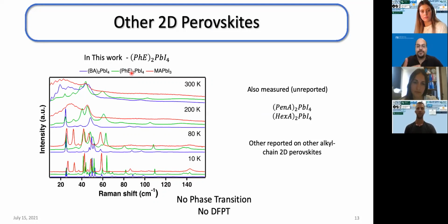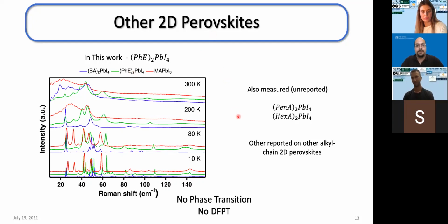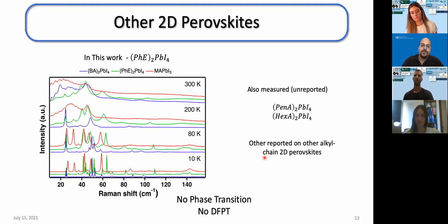Now, in this case, we couldn't do the DFPT calculations or any of this polarization orientation Raman because of the very low symmetry. What I can generalize is the fact that people have measured, I also measured other alkyl ammonium perovskites, the pentyl ammonium and hexyl ammonium, very preliminary results, but showing very similar trends. And other people have measured and did molecular dynamics calculations on other alkyl ammonium chains, and they all exhibit the same concept of phase transition. Most papers focused on the organic molecule, but again, our approach gives that the same phase transition, the same order-disorder concept happens in the inorganic layer and is related to octahedral tilting.